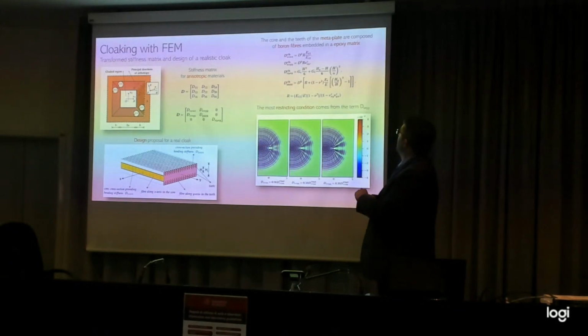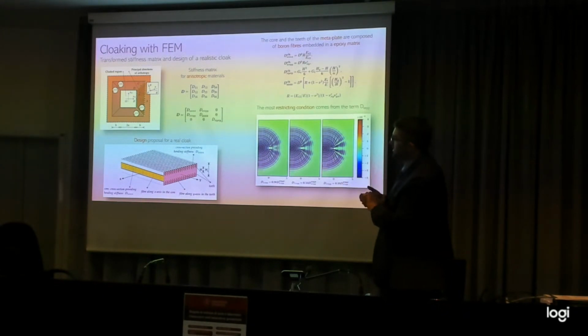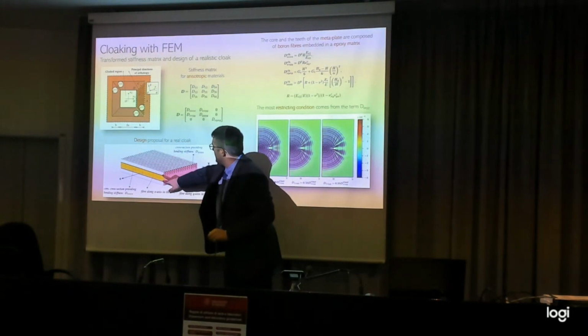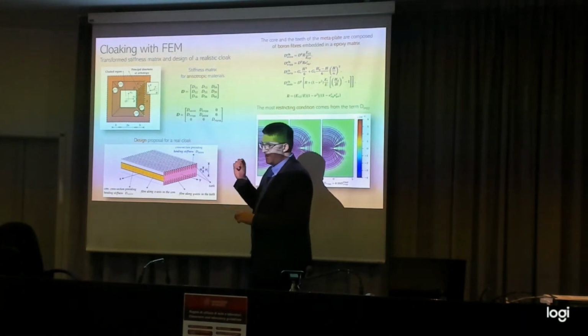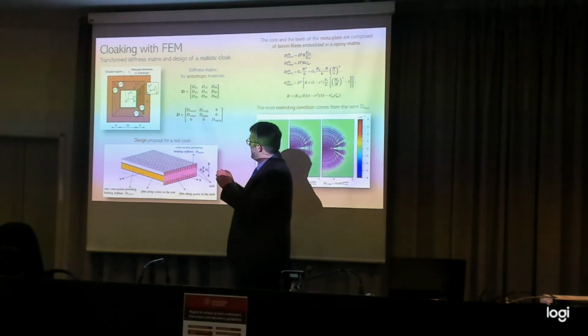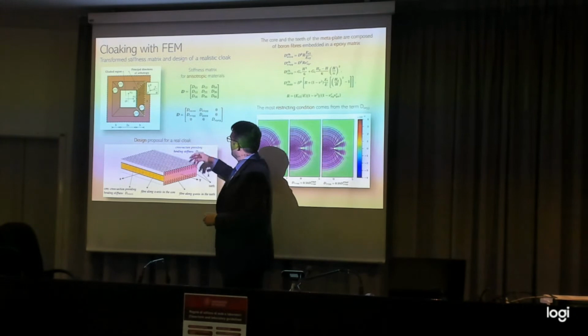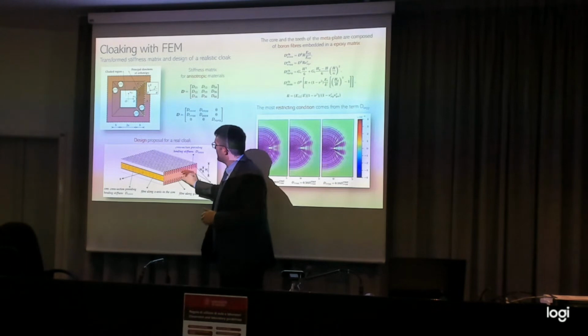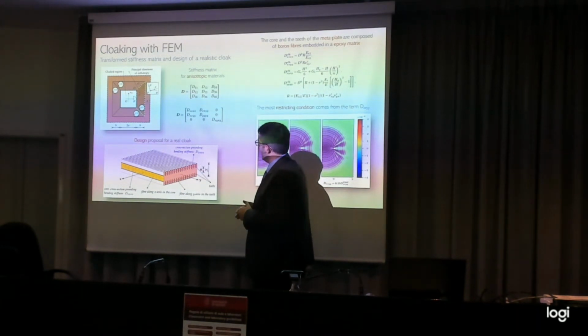So it's a metamaterial plate, let's say, composed of boron fibers embedded in an epoxy matrix. And so there is a core plate here, the one depicted in yellow. And this is the part that gives this torsional term. So this must be reduced. The height here should be very thin. And then, in order to obtain the other stiffness component, we had to add to this core a set of teeth in order to increase the stiffness along this direction.